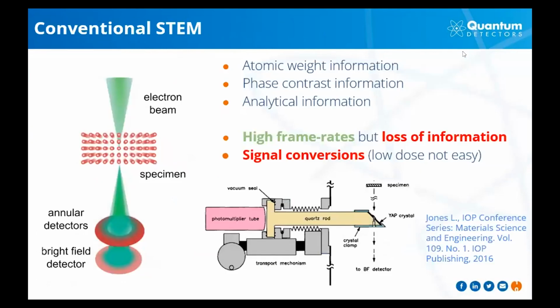So let's step back a little bit and talk about conventional STEM imaging. In this established STEM technique, the sample is rastered by a fine probe, as we see in the schematic on the left, and interacts with the sample, and we can detect the interaction after it passes the specimen. So this has been utilized for atomic weight information, phase contrast information, but also, with additional instrumentation, analytical information. Even though the conventional STEM detectors are fast, the distribution of scattered electrons, here we basically collect a few numbers. If this is a DPC detector, we get 4 or multiples, but we basically lose the distribution. It's averaged into a single or small number of intensities.